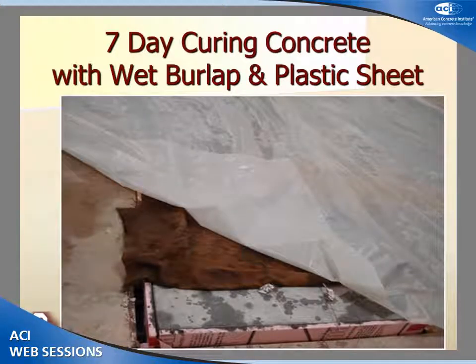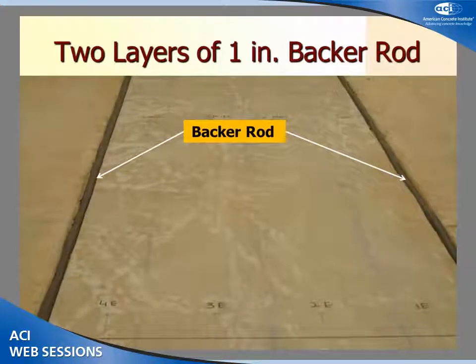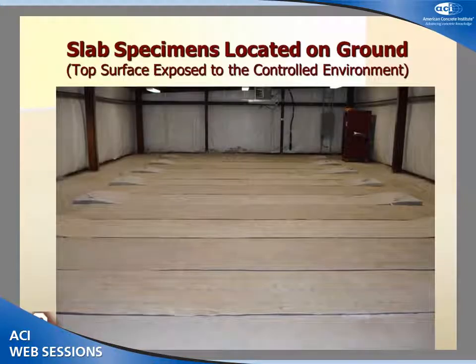We cured all the concrete slabs for 7 days with wet burlap and plastic sheet. After that, we removed the foam all around the concrete, and then we placed flexible 1-inch backer rod in 2 layers all around the concrete slab specimens. In this picture, you can see our slab specimens are located on the ground, and the top surface is exposed to the controlled environment.